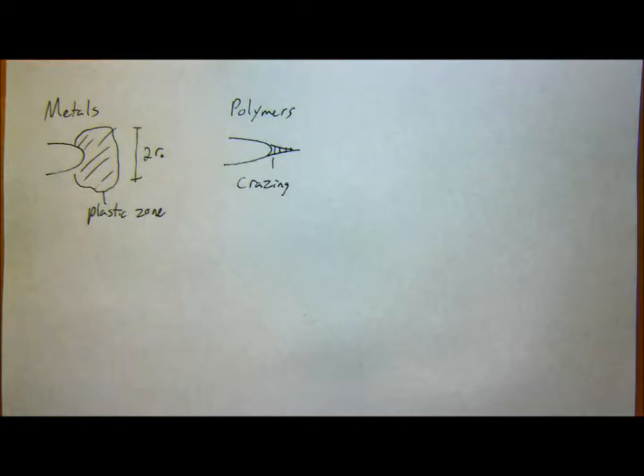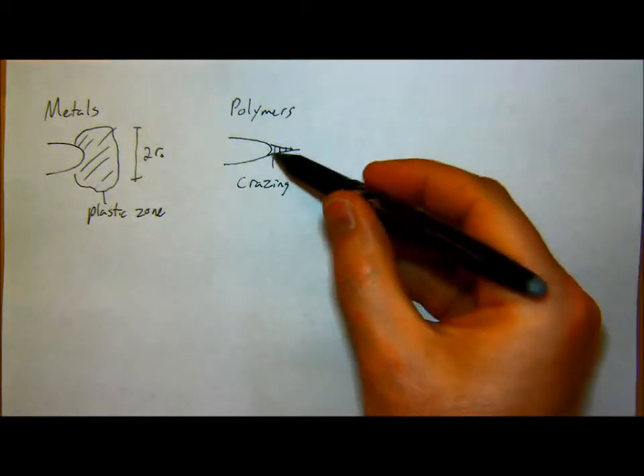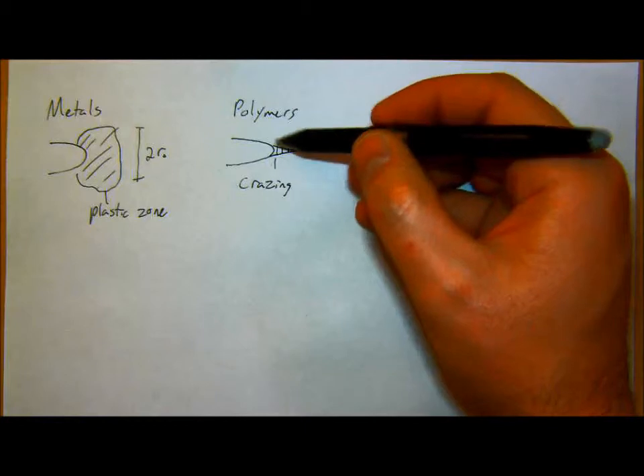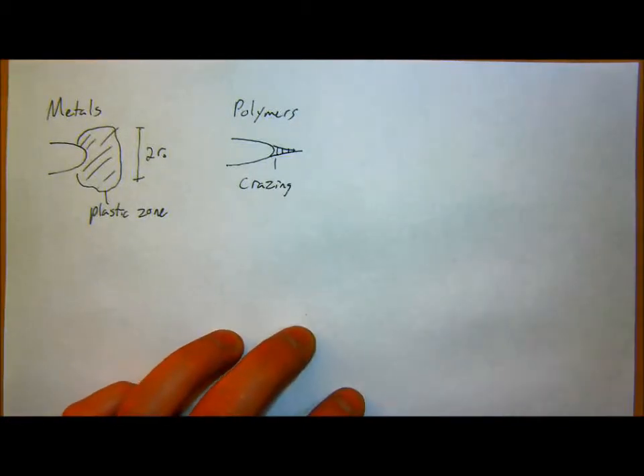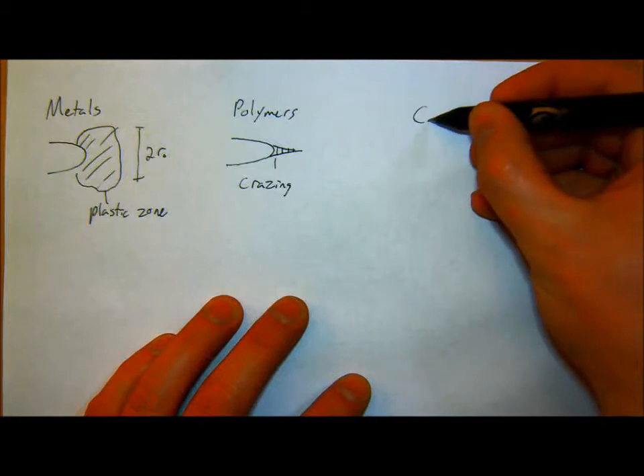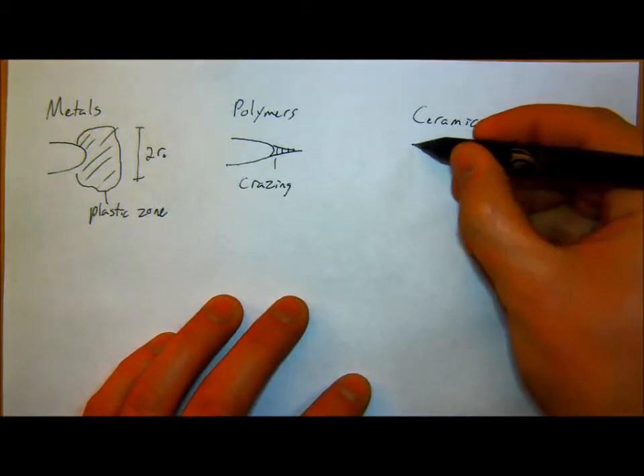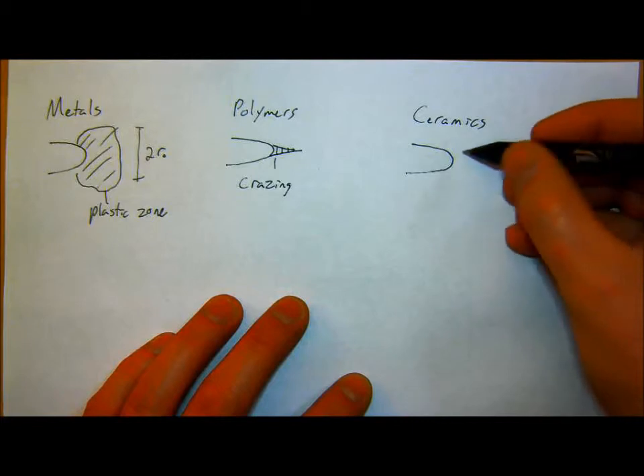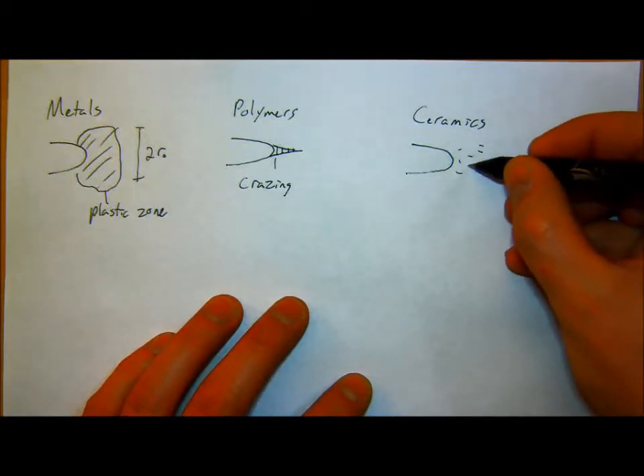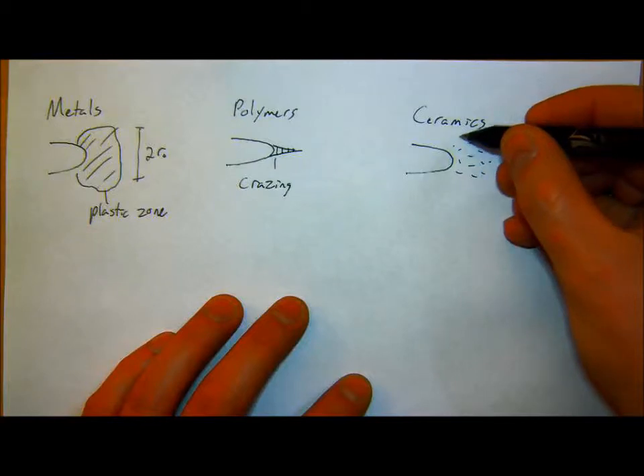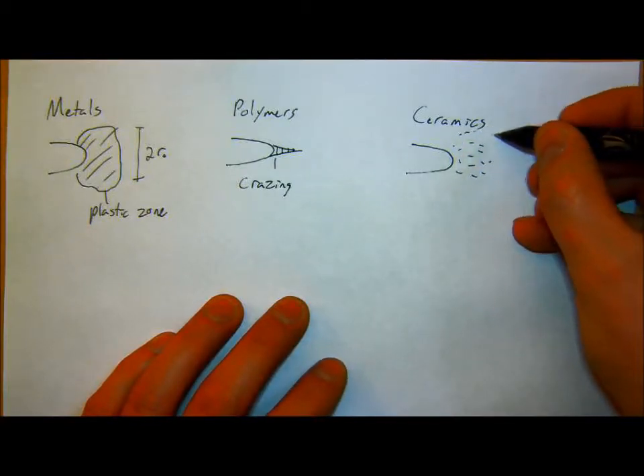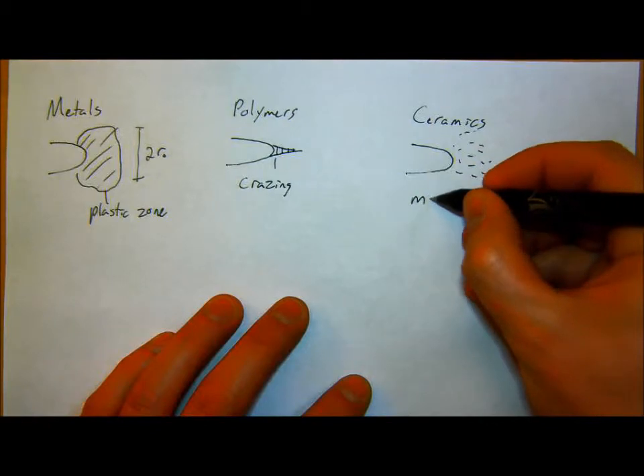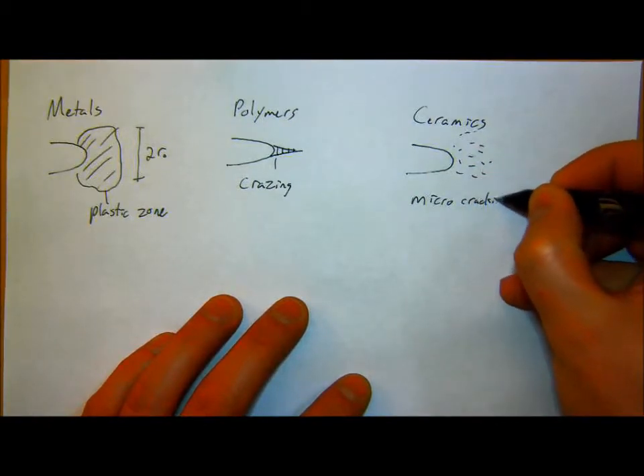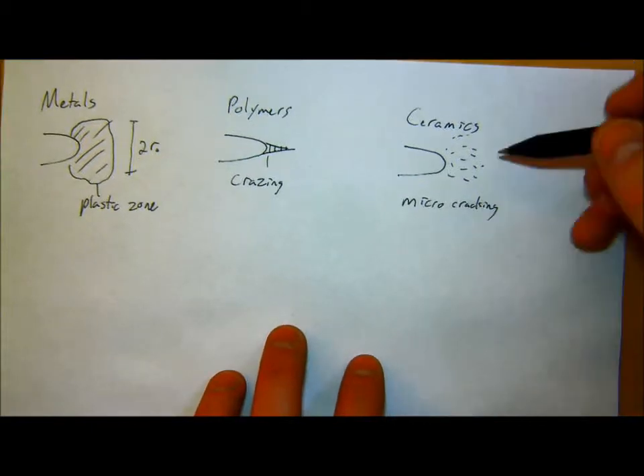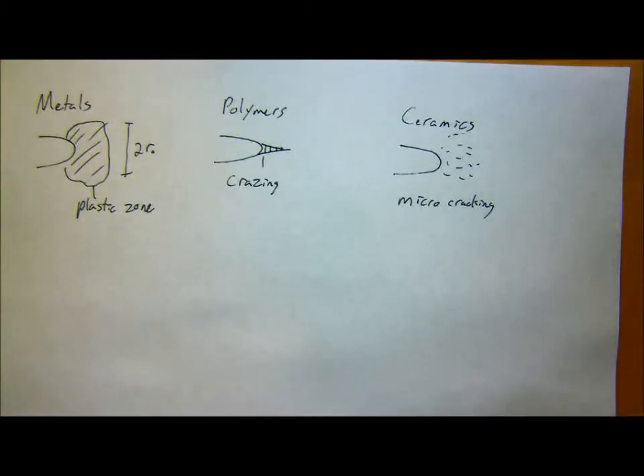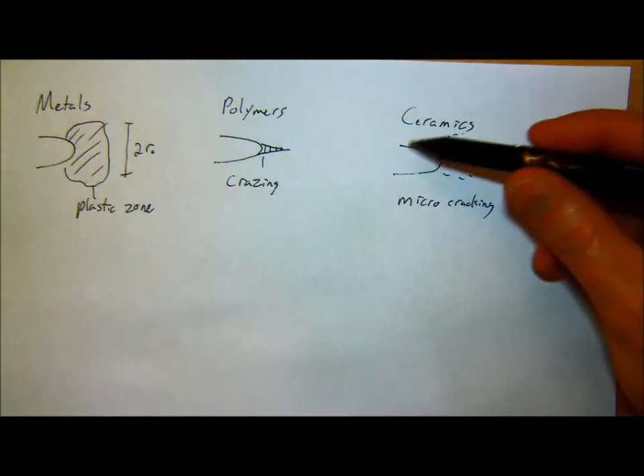For ceramics, around the tip of that crack there's a high stress. So what'll actually start to happen is in that zone around here, I'll get micro cracking. Because remember, ceramics are intrinsically brittle, they always have some small cracks internally in them. And so around the tip of a larger crack, I'll get micro cracking between different planes of atoms in there. So in that region of high stress around the tip, I'll get microcracking.